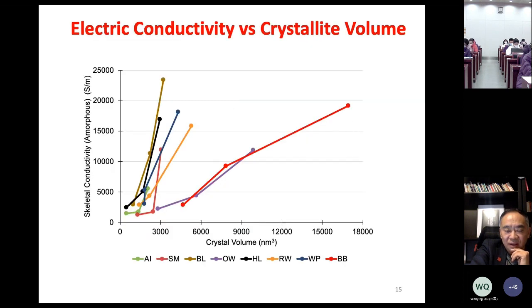Another interesting finding is that he found that the electric conductivity is highly dependent on crystal size, in this case, crystal volume. What we plot here is an increase of conductivity with crystal volume. Okay, what you can see is an almost linear relationship. Different colors indicate different materials here. The one point I want to make is that the maximum measured conductivity here is about 24,000, which is almost 10 times higher than graphite in the direction perpendicular to the graphene surface. Okay.